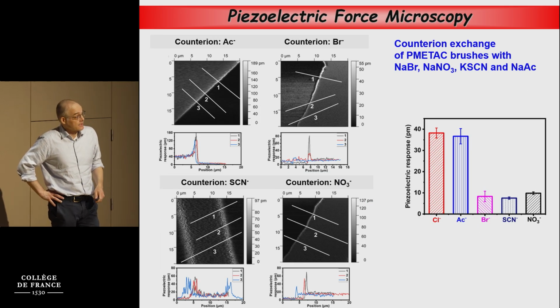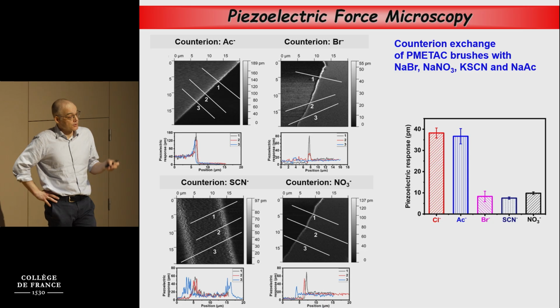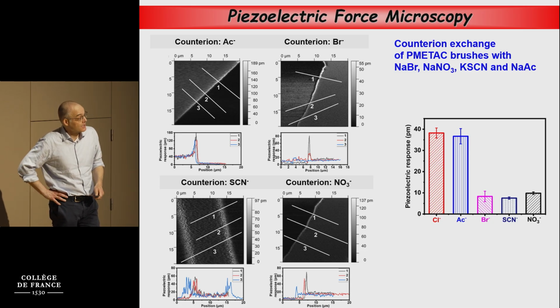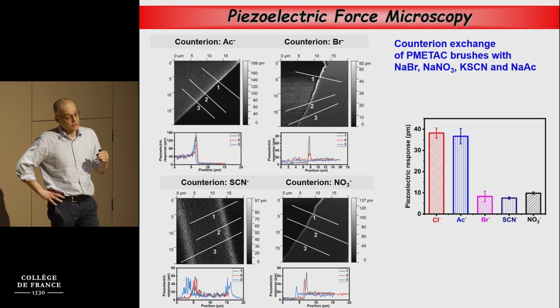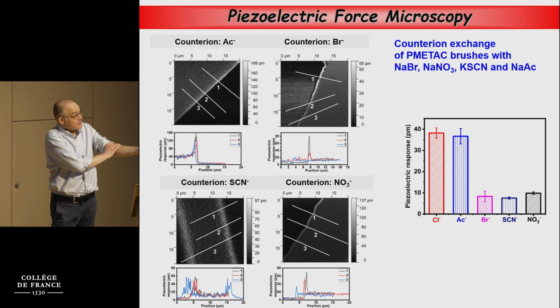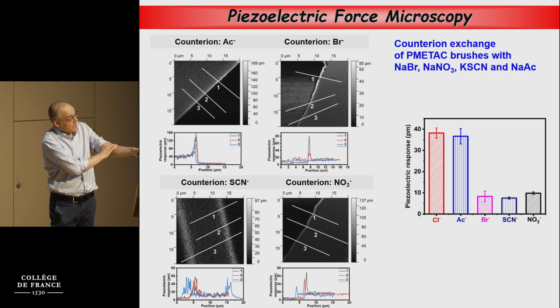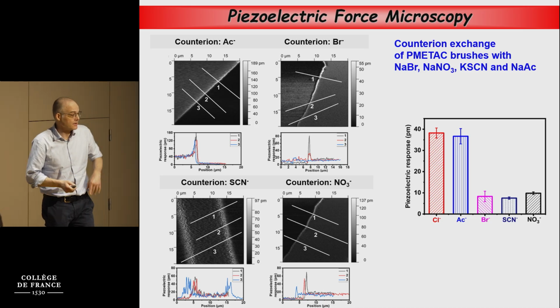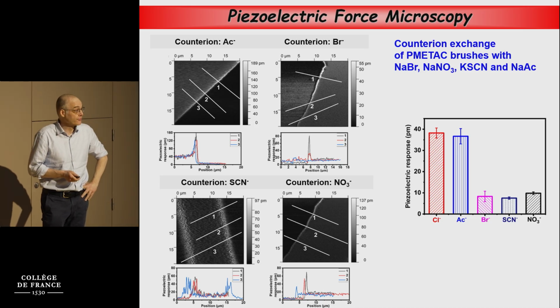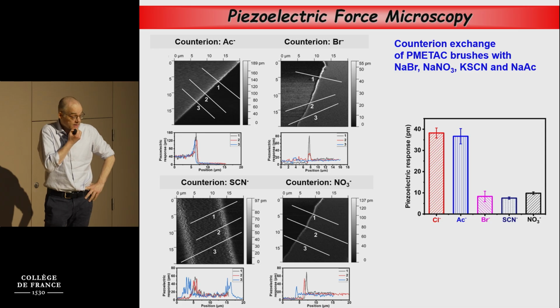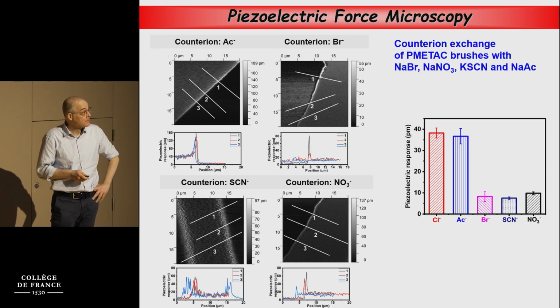We also looked with PFM at brushes where we exchanged the counter ions. And the results from the experiments were also in agreement with what we observed from the pyroelectric analysis, in the sense that the inverse piezoelectric response that we measured depends on the counter ion that is in the film. So the PFM results confirmed what we observed for the pyroelectric measurements.